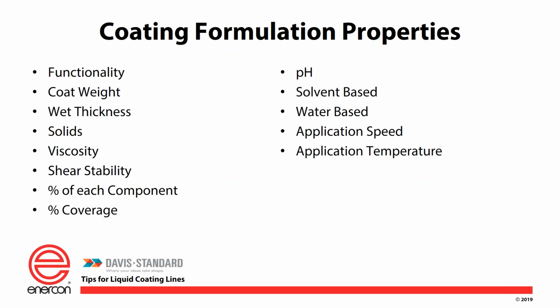And a wet film thickness is used to determine gaps, such as on a reverse roll coater, what is the gap between the two rollers? On a rod coater, what's the size of the wire that we're going to apply? On gravure coatings, what's the actual cell formation of the gravures that we need to apply it to? And again, through the thicknesses, we figure out how much of this we have to evaporate out. Solids is the actual part of the coating that, once you're dry and you wind it up, is the part that's left on the sheet.